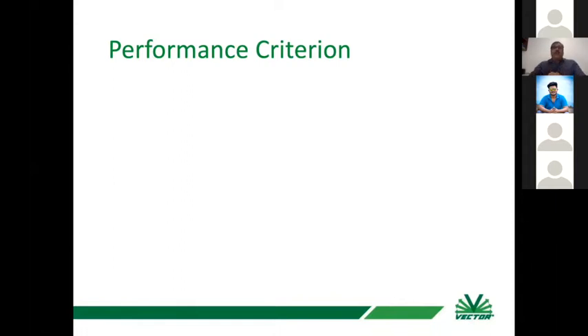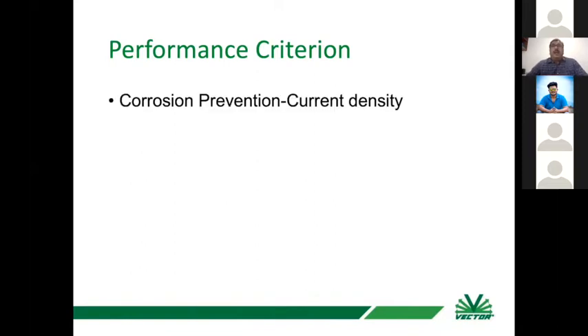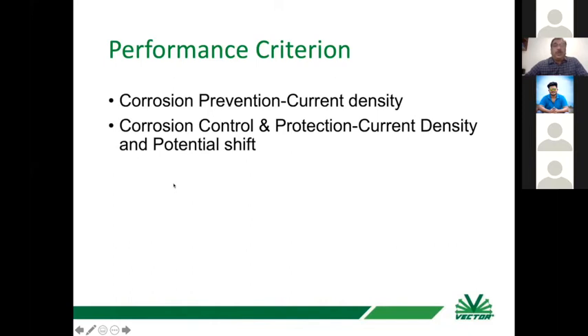Regarding the performance criteria: once you design the system, how should one know, as a designer, in which way my cathodic protection should perform? How can I say that yes, it is performing? When you are doing corrosion prevention, then current density comes into the picture. EN 12696 says to apply a current of 0.4 to 2 milliampere per square meter of steel surface area, then you are preventing the corrosion from initiation. So that is current density in the case of corrosion prevention. In the case of corrosion control and protection, there is current density as well as potential shift, that is depolarization. If you are able to depolarize by more than 100 millivolts in 24 hours of the system, then you are protecting your structure. So these are the performance criteria.